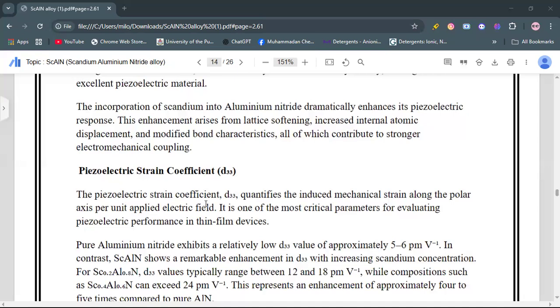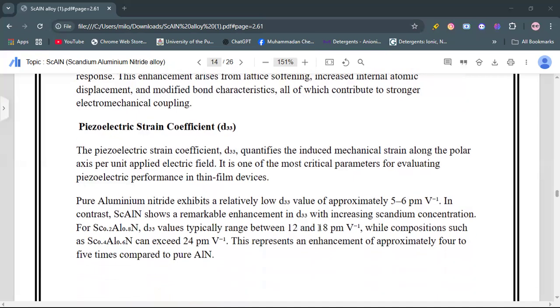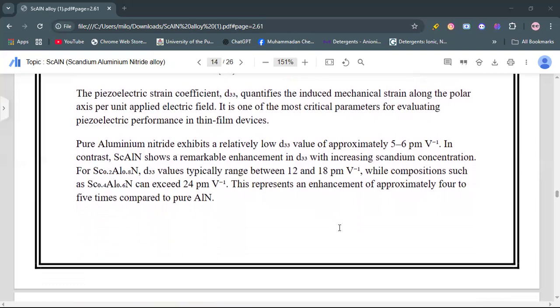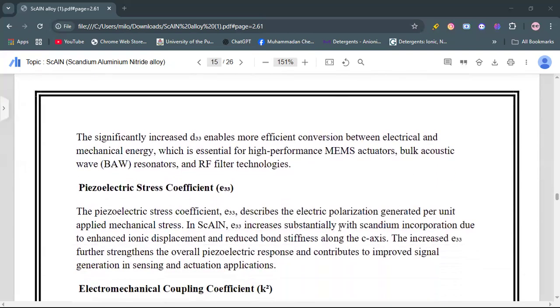Pure aluminum nitride exhibits a relatively low piezoelectric strain coefficient, which is 5 to 6. In contrast, scandium aluminum nitride shows a remarkable enhancement with increasing scandium concentration, and the value ranges between 12 and 18 picometers per volt. This represents an enhancement of approximately 4 to 5 times compared to aluminum nitride. The significant increase in piezoelectric strain coefficient enables more efficient conversion between electrical and mechanical energy, which is essential for high performance MEMS actuators, bulk acoustic wave resonators, and RF, which is radio frequency, filter technology used in 4G and 5G communication.